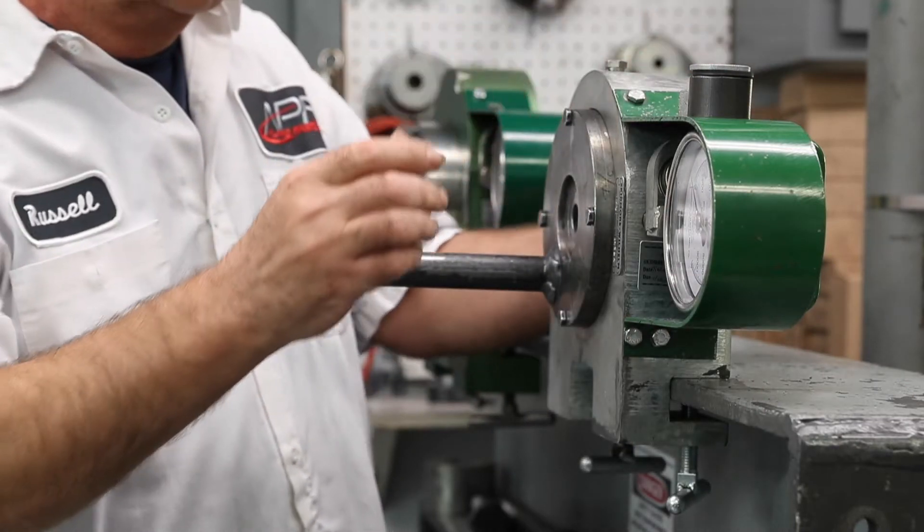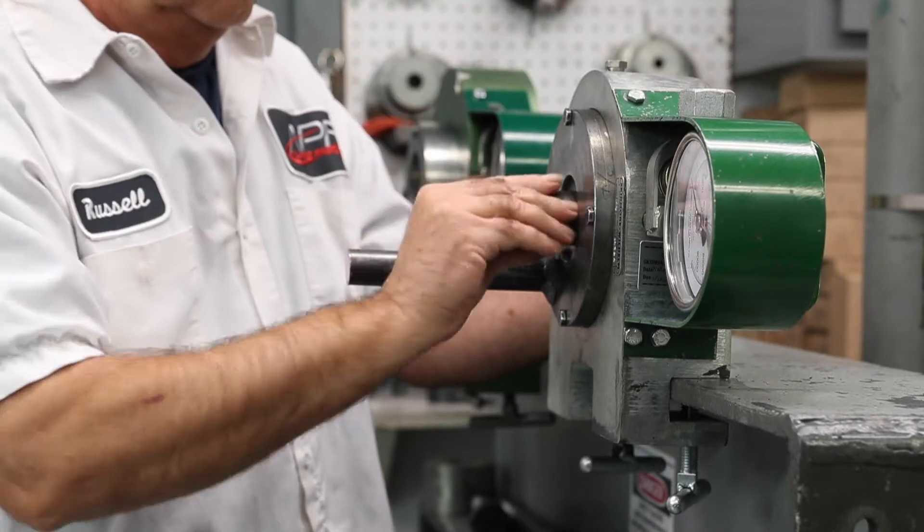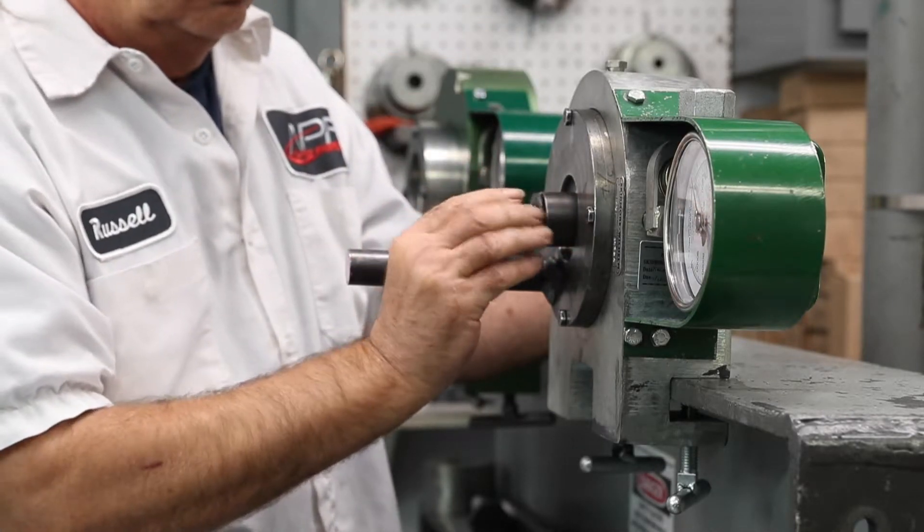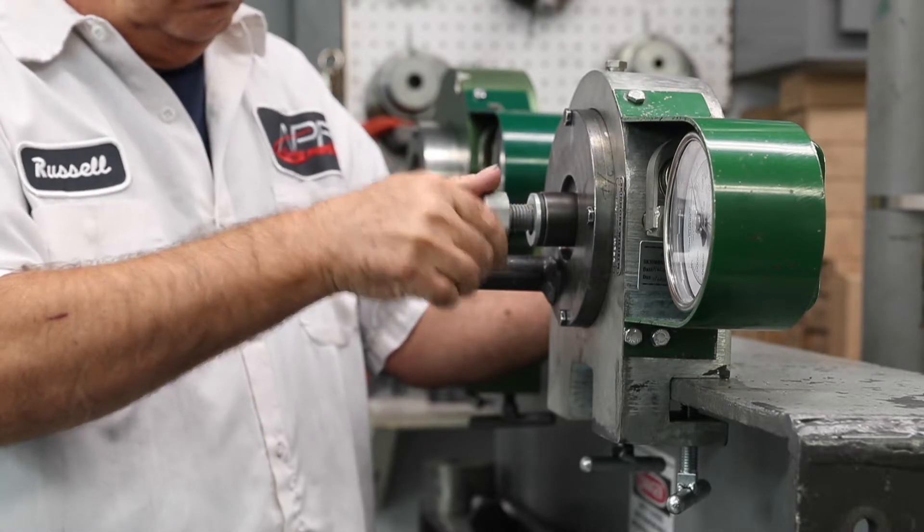To begin, the bolt is installed in a tension measuring device. If required, spacers may be used so that the bolt is flush with the nut to a maximum of three-thread stick-out. This setup will typically provide three to five threads within the grip.